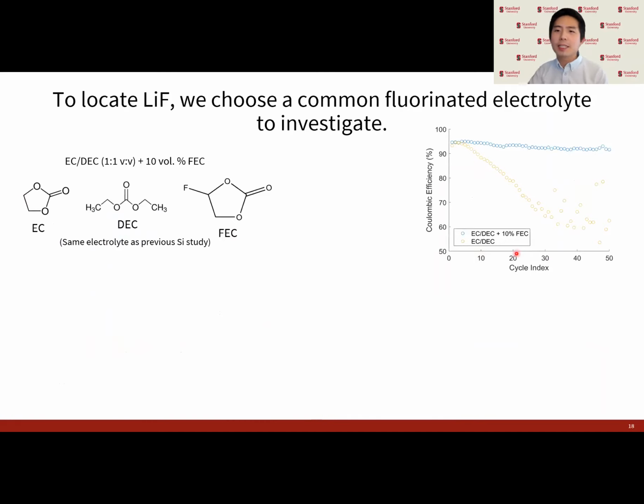So to address this knowledge gap, we'll carry out this experiment on the lithium metal SEI using the same fluorinated electrolyte system that we used previously for silicon. And that's this ethylene carbonate diethyl carbonate electrolyte with the 10 volume% FEC additive. And similar to silicon, with the addition of the FEC additive, we can further stabilize the lithium metal cycling shown here. And this is commonly attributed to this defluorination reaction, generating a lot of lithium fluoride in the SEI.